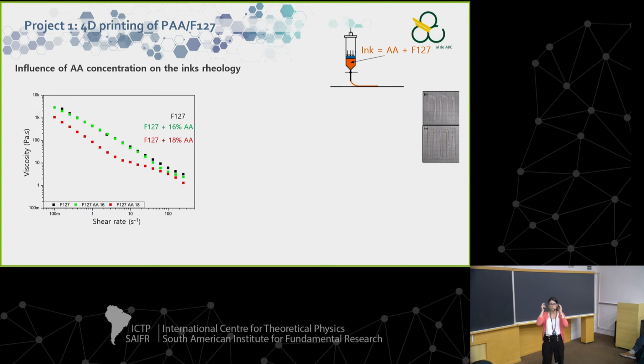So of course we need to look at rheology. First, we measure the viscosity as a function of the shear rate. In all cases, we get a shear thinning behavior, which is adequate for printing. We need this decrease of viscosity when we apply a shear rate.